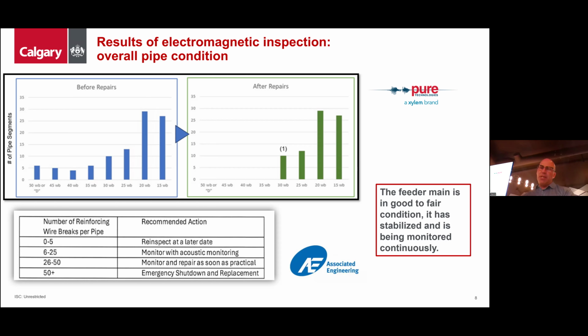The city completed repairs to 29 pipe segments from the time of the break on June 5th right through November of 2024. As you can see in the chart, these actions have resulted in the repair of the segments of pipe that had the most significant structural deficiencies. You can see, as provided by Associated, this is the criteria that we use to determine which recommended action to take from a risk-based approach.